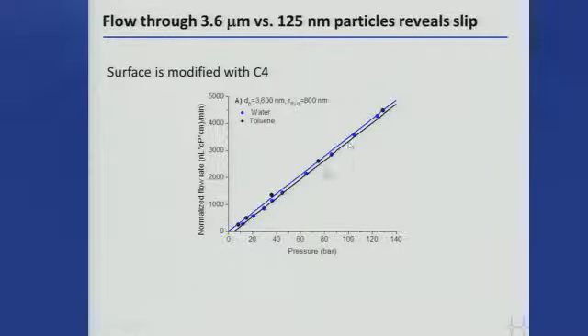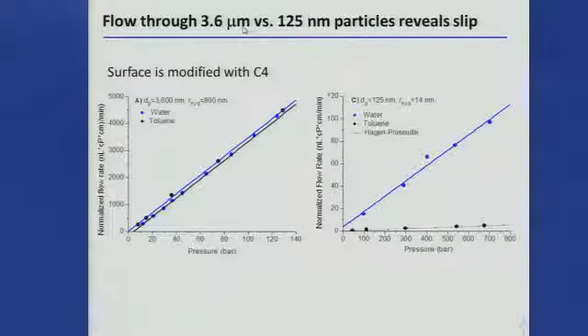really well. You know, the instrument always gives a little bit of an offset, but these overlap within error. So flow versus pressure, water and toluene line up really well with 3.6 micron particles. If you go to really tiny particles, 125 nanometers, this is what you get. So now, again, normalized for viscosity, that's water, that's toluene. And the dotted line, again, is the Hagen-Poiseuille flow, so predicted theoretically. Again, it lines up really, really nicely with this. So toluene has no slip flow, and water has huge slip flow. The slopes differ by a factor of 20.